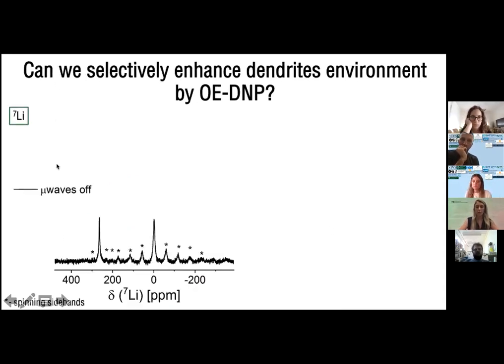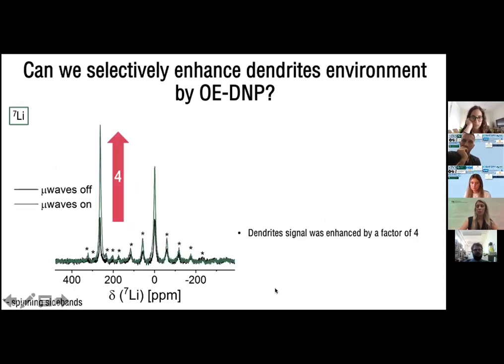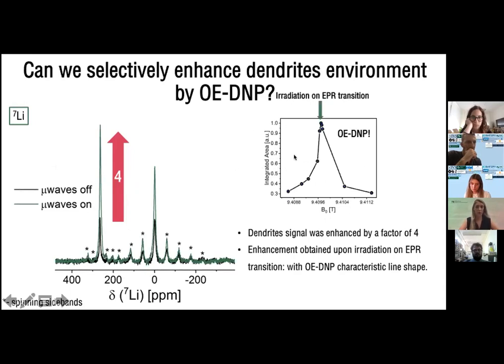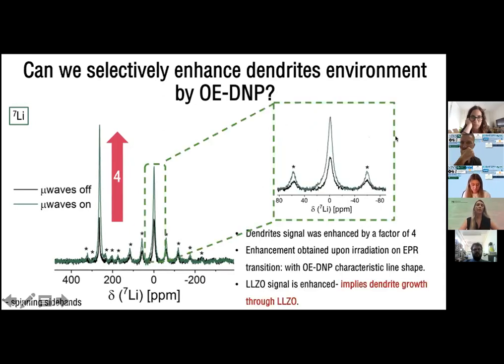So this is a microwave off of our cell of lithium 7. As we turn the microwave on, we can see signal enhancement of the dendrites by a factor of 4. And we can verify that it is an Overhauser DNP because the irradiation on the EPR transition gives this characteristic nice line shape. And surprisingly, what we also saw is that the LLZO signal here was also enhanced. It probably implies the dendrite growth was through LLZO, because with microwave on, we see that this signal is enhanced.